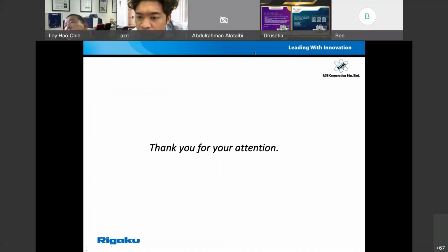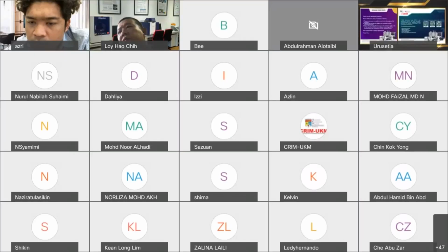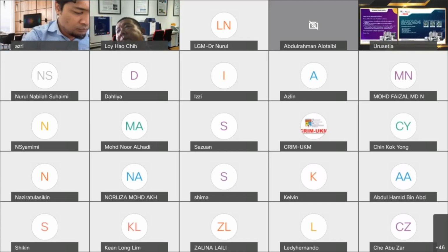So we have a question already. Is the software able to correct preferred orientation? No. Actually, for WDXRF, if your samples have a preferred orientation, what we can do is normally spin the samples. This is one of the reasons why we do spinning, but even that will not help much with preferred orientation. Normally preferred orientation is an issue for XRD.